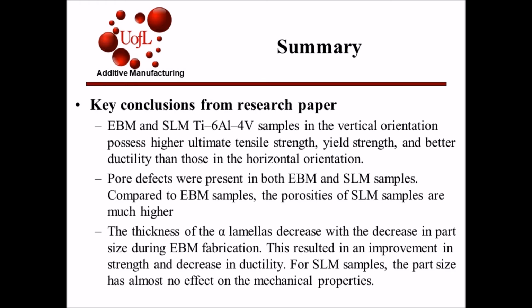And the third conclusion was that the thickness of the alpha lamellas decreased with the decrease in part size during EBM fabrication as a result of the faster cooling rate. This resulted in an improvement in strength and decrease in ductility. For SLM samples, the part size had almost no effect on the mechanical properties.